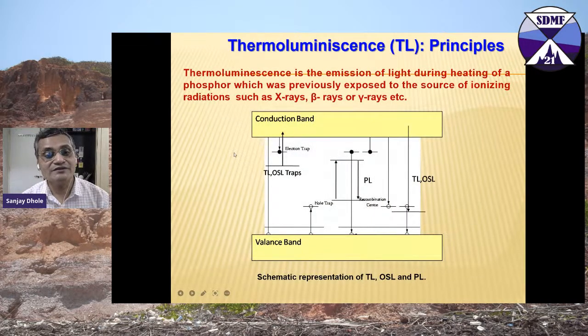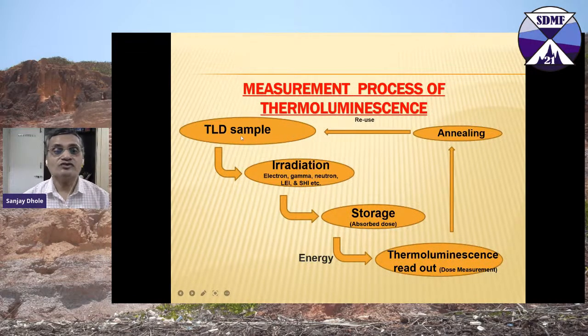So this is again the same thing. You have a TL and OSL trap over here, you have a PL, you have TL all together. This is the conduction band. The measurement process of thermoluminescence: the TLD sample, irradiation with electron, gamma, neutron, low energy electron, ion and swift heavy ions, then storage. The energy is released here as thermoluminescence, and then you can anneal that sample and reuse it again. The TLDs can be used initially to measure the dose and be annealed out. All those traps can be detrapped and made available for the measurement of another set of radiation. So the same TLD can be reused.